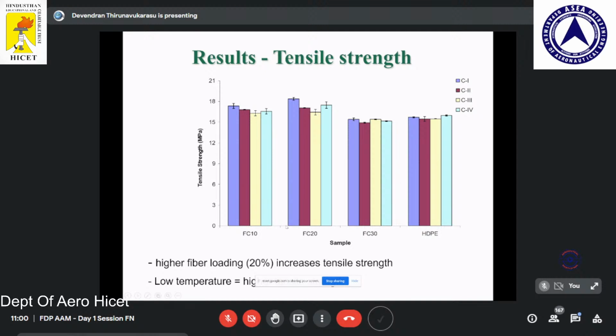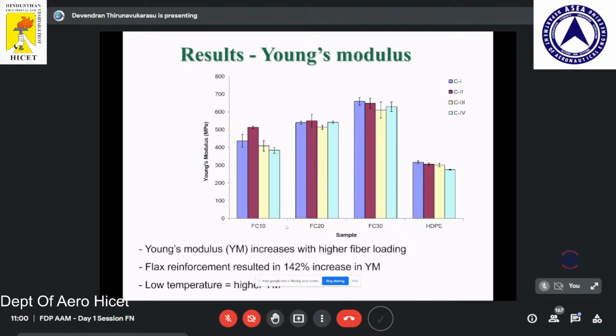This is the flexural strength. Sorry, it's the Young's modulus from the tensile test. The Young's modulus increases with higher fiber loading. The strength is highest in FC20, which means the 20% flax composite has good tensile strength. And the higher volume content gives a good Young's modulus, so the stiffness of the material is high.